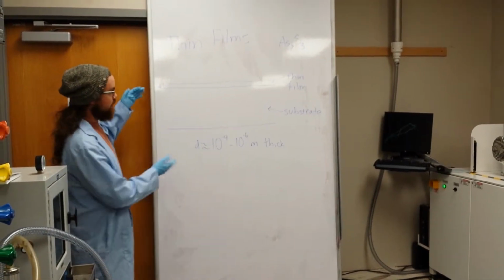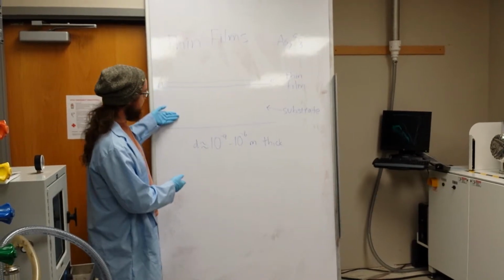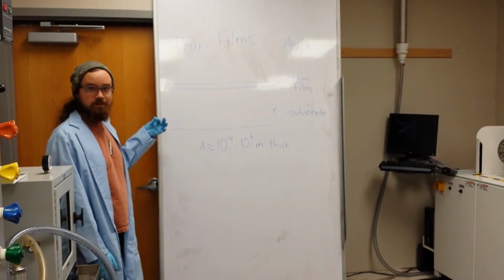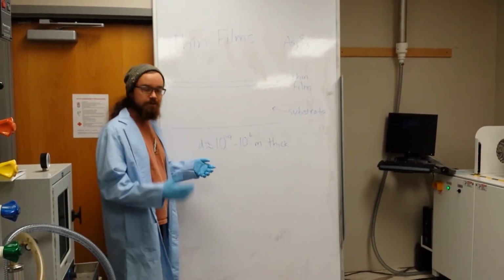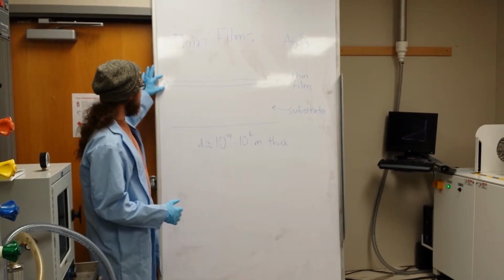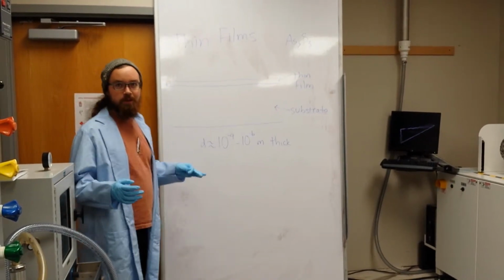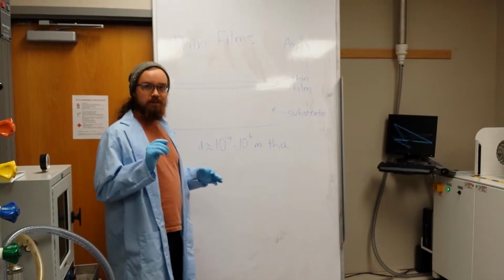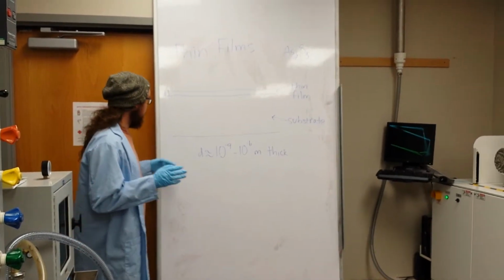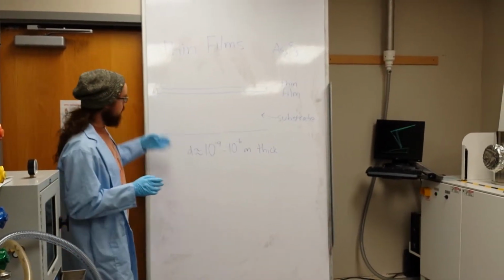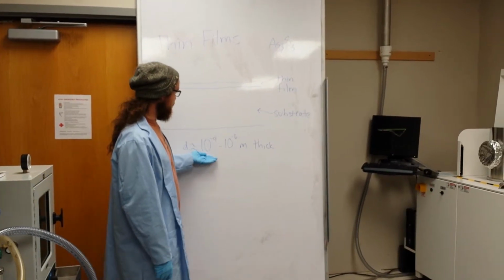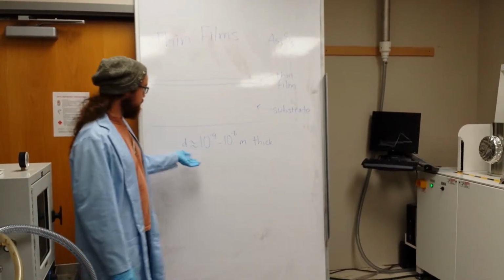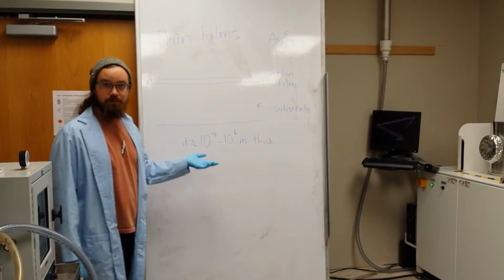So here's a schematic of a thin film. This large region down here is what we call the substrate, which is the material that we deposit the film onto. And then this thin layer on top is the actual thin film. The thickness of the thin film is much less than that of the substrate. So the thickness here, D, for thin films is typically on the order of nanometers to microns, which is 10 to the minus 9 to 10 to the minus 6 meters.